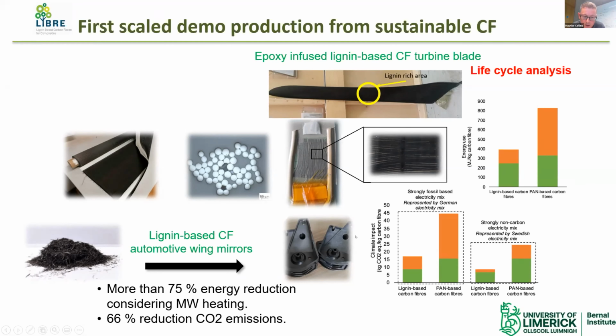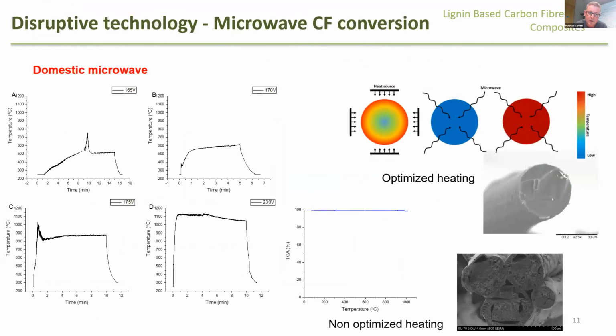All this was done, and we did some life cycle analysis on this as well, and we produced a 75% energy reduction considering microwave heating, which I'll talk to you about in a second. And there was a 66% reduction in carbon emissions. We got these life cycle analysis data based on the fact that we were using fully sustainable carbon fibers, but also the fact that we use a microwave technique to produce these fibers rather than conventional heating.